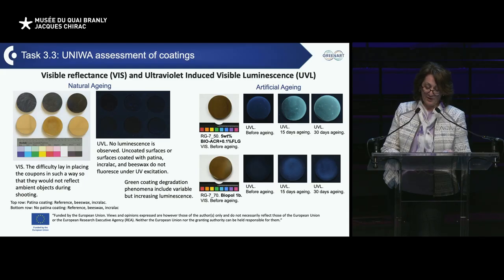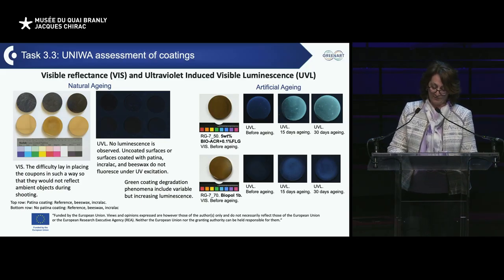Ultraviolet-induced visible luminescence can prove to be very helpful in monitoring metal objects. Metal surfaces usually absorb UV radiation and do not produce any fluorescence. Unfortunately, some conventional coating materials, such as beeswax and Incralac, which you can see in the image on the left, exhibit similar behavior and do not fluoresce. However, new green materials, as you see on the right, exhibit fluorescence. Differences in intensity and color of illumination can be indicative of the material used and of the degradation of the material.